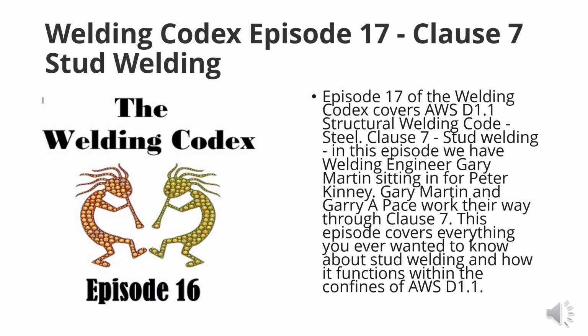Examples of stud applications using mechanized welding that require test of this section are the following. So it lists three criteria: studs which are applied in non-planar surfaces or to a planar surface in the vertical or overhead position. So you can't pre-qualify vertical or overhead. Studs which are welded through decking. Test shall be conducted using the thinnest base metal thickness used in construction, but no thinner than ½ inch.